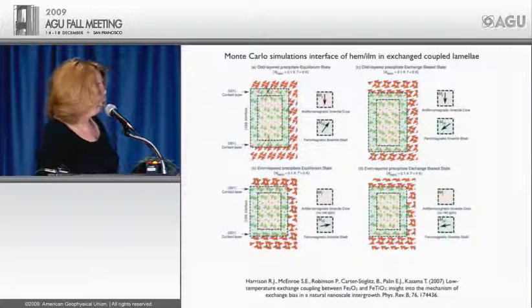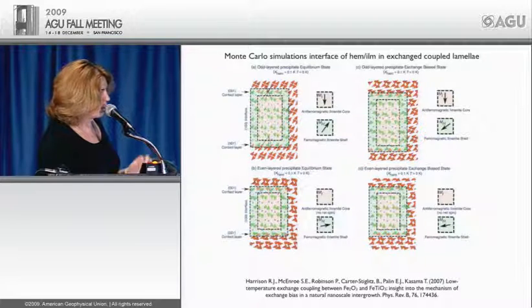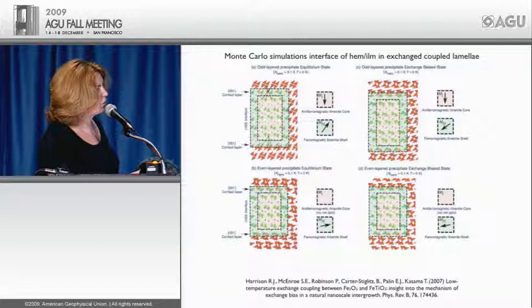Shown here is a Monte Carlo simulation of trying to understand how the material shifts. We have an equilibrium state, and we also have the shifted state. When we have an odd number of lamellae at the core, so we have a shell and core, we will get a shift. When we have an even number, they'll both rotate and you'll end up with no shift in the loop. This was the first step in trying to understand which moment was shifting, and we thought there was a very good chance that the hematite was rotating out of the basal plane. We thought this also because the anisotropy of the ilmenite is extremely high compared to the hematite.